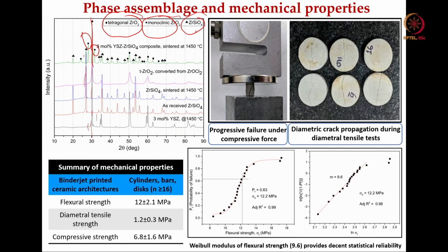The zirconium silicate or zircon sand that we have mixed with the zirconia during the 3D binder jet printing, or in the powder bed itself, certainly remained there even after sintering at 1450 degrees Celsius. As I have mentioned, in some of the cases we have used a salt like zirconium oxychloride, and when you use zirconium oxychloride you get more full conversion to tetragonal zirconia. You do not see any other phases except tetragonal zirconia, and monoclinic zirconia is not there. No monoclinic zirconia, that is important, because if you have monoclinic zirconia, that compromises the strength, hardness and toughness properties of zirconia.